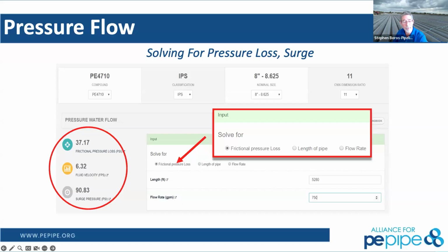But the nice part of this is polyethylene can handle that. Even an instantaneous surge pressure would only be 90 psi. If you're operating at 100 and you have a 90 psi surge at that 6.3 feet per second flow velocity, water hammer effect, you're only going to have 190 or maybe 200 psi. That's well below even the pressure rating of the product, which in this case can go up to 400 psi. So even under those conditions, you're going to be just fine. So you can look at different situations like that to see what works. Is it going to be a valid design for what I need?